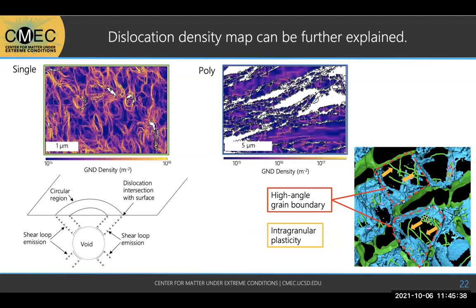And so I'm just going to touch one more thing on these two maps. In the single crystal, you can see that the regions of high dislocation density in the orange color are really, really obviously circular. And so we explain that in our paper as some void in the subsurface that had emitted dislocations in a spherical manner. But when we're looking at a 2D cross-sectional map of it, we actually see circles. And so that was a really cool correlation we found.